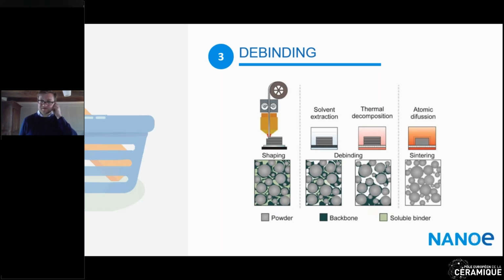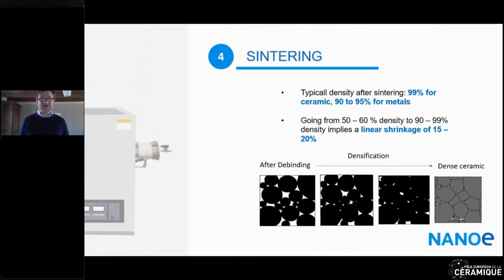And then once you have burned this binder, you will have what we call a brown part or a debinded part, which is extremely brittle and which must be sintered to get to the final mechanical properties. What happens during sintering? Sintering means going to high temperature, a bit lower than the melting temperature, but still relatively high, to get to a dense ceramic or metal.